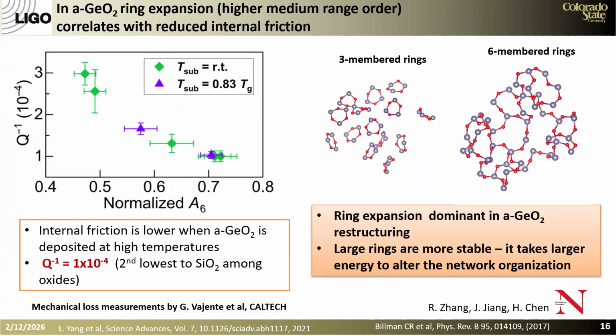So then we plotted the area of the 6-member rings, and we took that as the parameter. This indicates higher network organization, and we measure internal friction in the coatings, and we saw that there is a reduction in the internal friction. And this is what we need to make good coatings for gravitational wave detectors. In fact, we measure an internal friction, which is the second lowest compared to silica among all of the oxides.